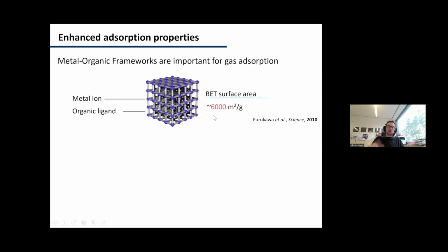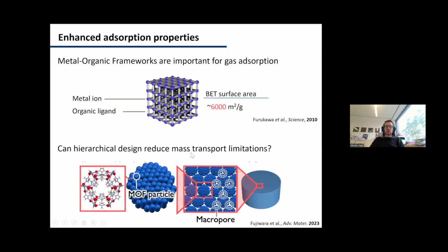And here's a second example. This is about adsorption. Metal organic frameworks are very important materials for gas adsorption because they have very, very large surface areas. But the problem is that when you use these in bulk, the pores are very poorly accessible because gas needs to squeeze into this framework over large spacings. And the question here was whether we can introduce a hierarchical design to reduce mass transport limitations. So in a sense, make metal organic framework primary particles, put them into a superparticle, stack the superparticles into a pellet, and then assess how this hierarchical pore structure affects the transport.